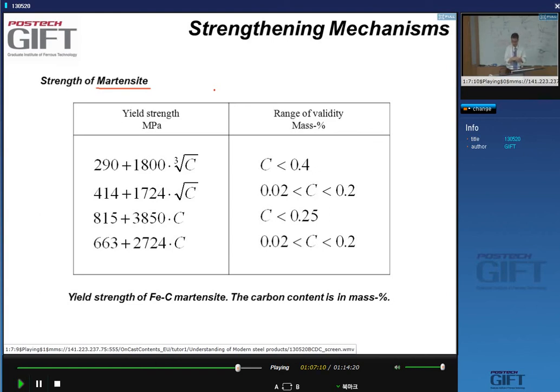But the most important parameter influencing the strength of the martensite is the carbon content, yeah? And there have been different equations proposed for the strength of martensite, but in general, what people report is a very strong relation between the strengthening and the carbon content. I show you these equations here. They're experimentally measured, so you definitely don't learn them by heart.